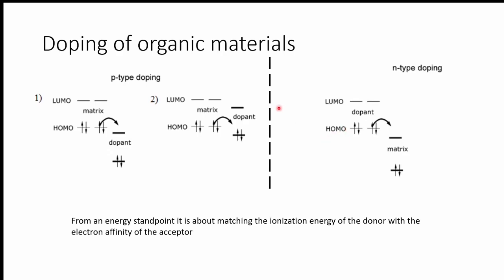And what can happen is one of two things. If you have an electron-rich polymer, you'll have that polymer donate an electron into your dopant, your impurity, and then basically the absence of this electron will induce charge transfer because then it can accept an electron from a neutral polymer that exists in the matrix.